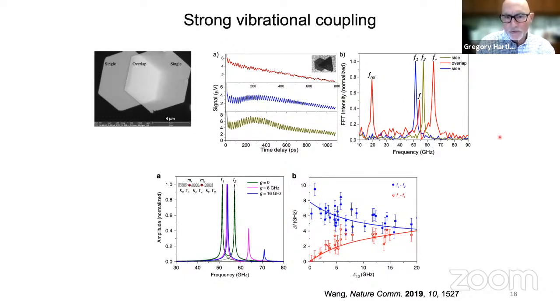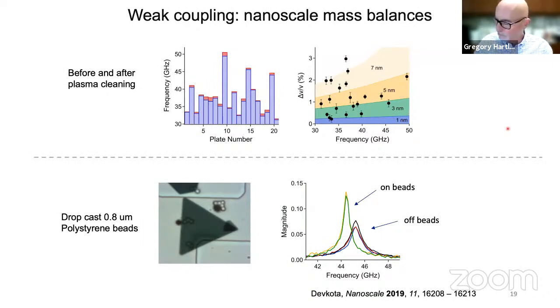The other thing that we can do with these resonators that have very high quality factors is look at what happens to the frequencies when we add or subtract mass. The top graph here shows frequencies for some nanoplates before and after plasma cleaning. Plasma cleaning, for us, was meant to take off all the organic material that's on top of the plates. When you make these plates in solution, they are coated in surfactant. If we remove the surfactant, we see that there's always an increase in the frequency. This is a mass loading effect: when we take mass off the plates by cleaning them, the frequency goes up. These are the experimental results calculated as a relative difference in the frequency versus the frequency of the vibration.